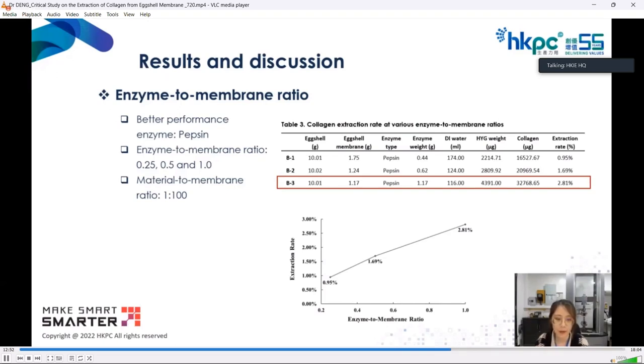As shown in the figure, with this ratio increasing, the substrate hydrolysis reaction becomes more complete. The collagen extraction rate significantly improved from 0.95% to 1.69%, with the ratio increasing from 0.25 to 0.5. By increasing the ratio to 1, the collagen extraction rate increased slightly to 2.81%, and the growth rate gradually decreased.